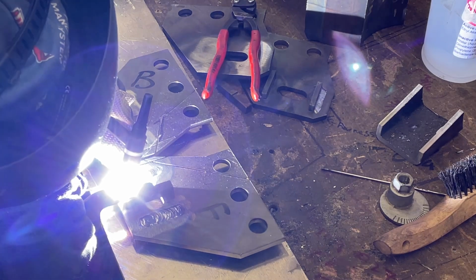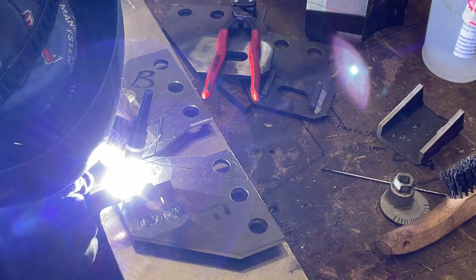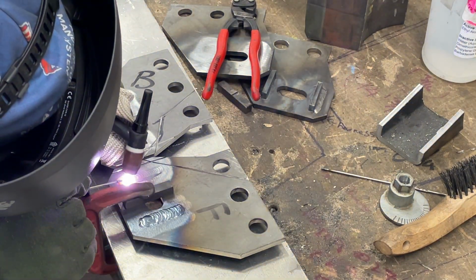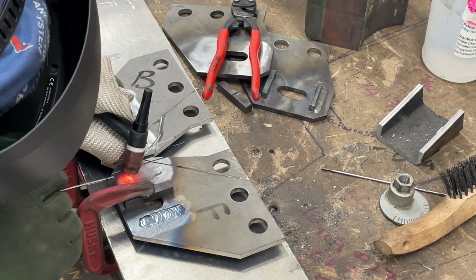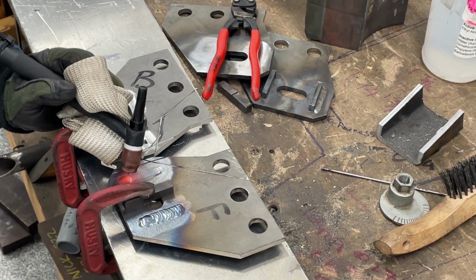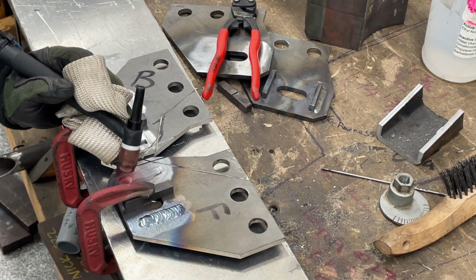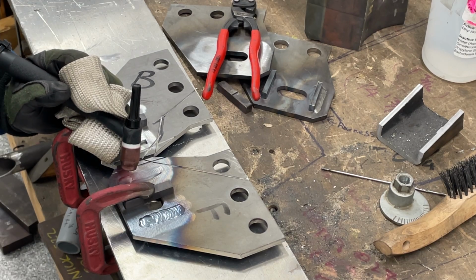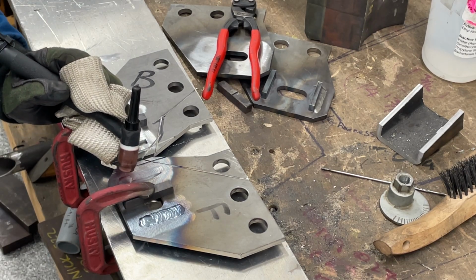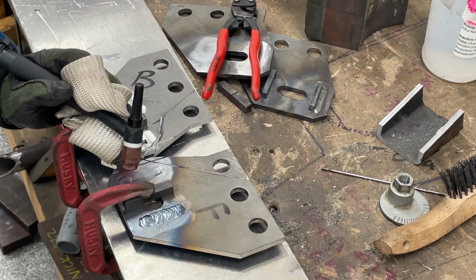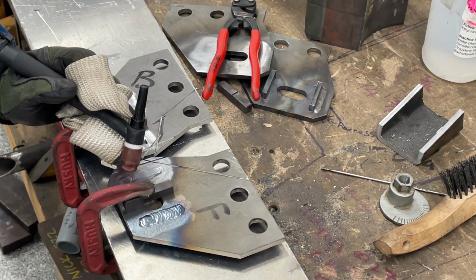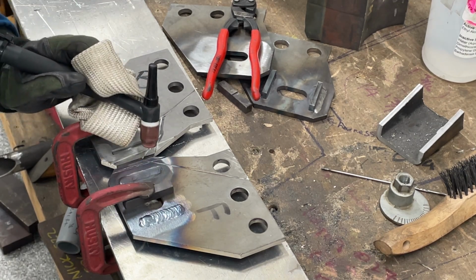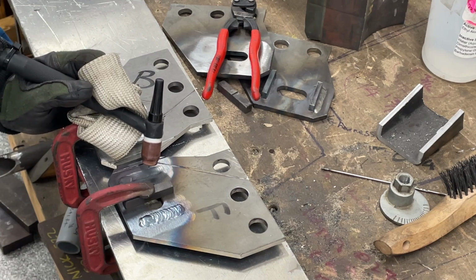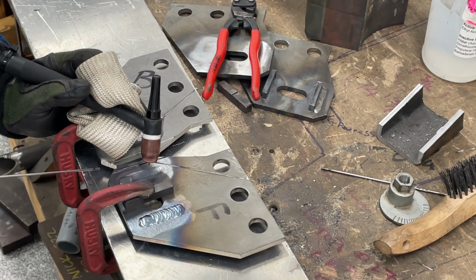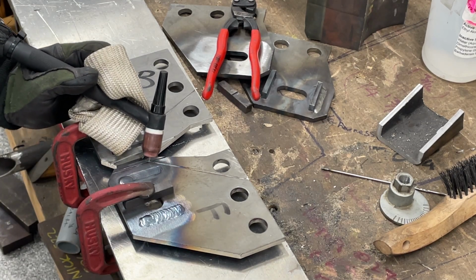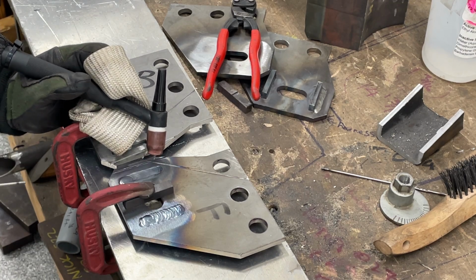Okay, fill up that start and stop. Give it a little whirl and a slow stop. Again, the slower your arcs stop, the less solidification cracks you're going to have, and the less grinding of your starts and stops you will need. Now, if you're doing like phased array criteria or a liquid penetrant criteria, that'll be the most likely place to fail. So keep that in mind if you're doing this in an industrial setting.